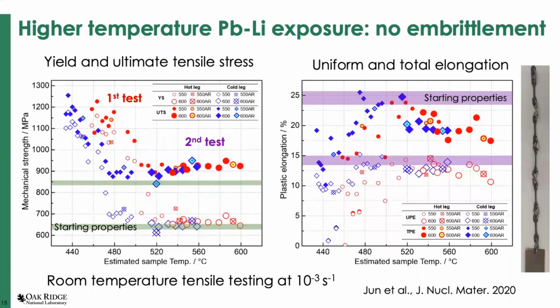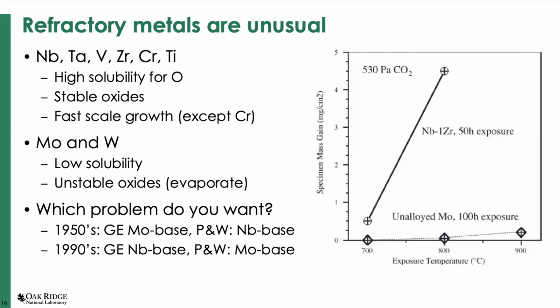And finally, when we did our next experiment at a higher temperature, we didn't see any of this effect. As we went to higher temperature, we got away from that embrittlement range, and now we didn't see any instance of really strong loss in ductility or change in the yield or ultimate tensile strength. The shaded areas in each of these plots is the starting properties of the APMT material. And this was reported a little more recently, again, in the Journal of Nuclear Materials. And again, chain of specimens so that we have different temperature exposures for each of the specimens in these 2 experiments. Now, let's get back to refractory metals.